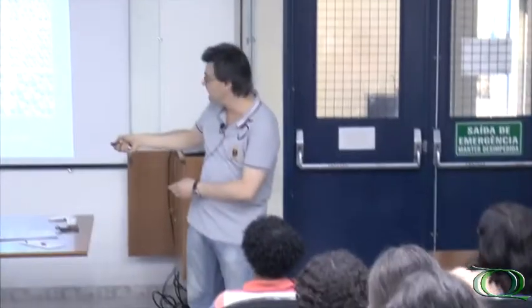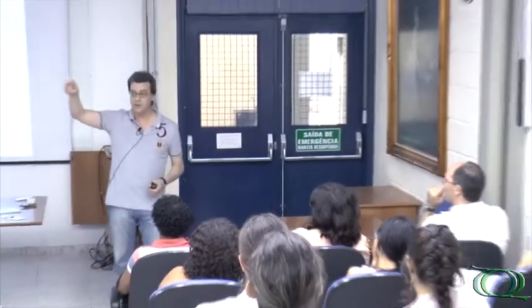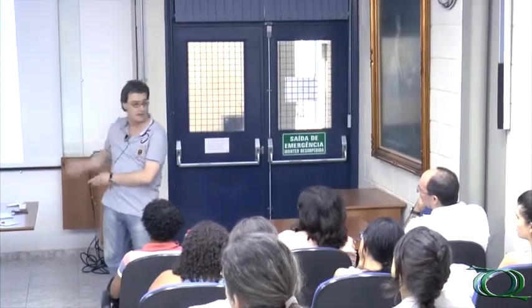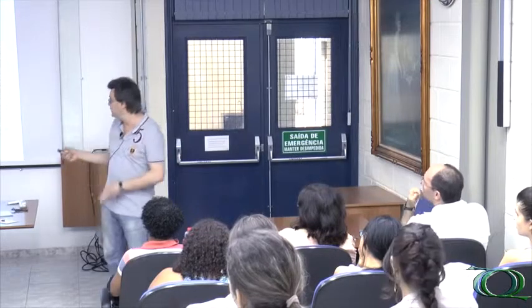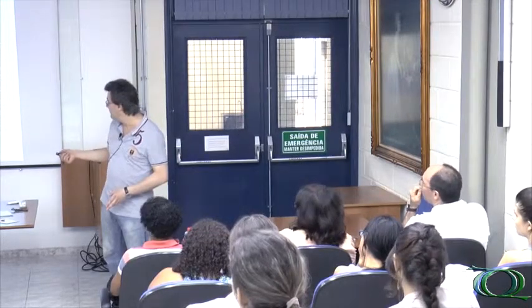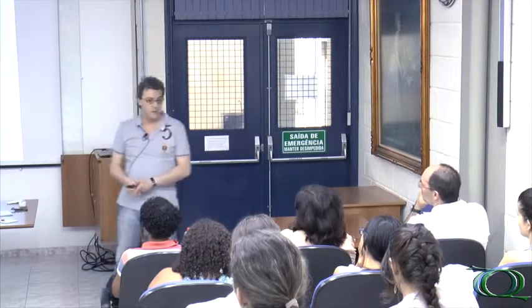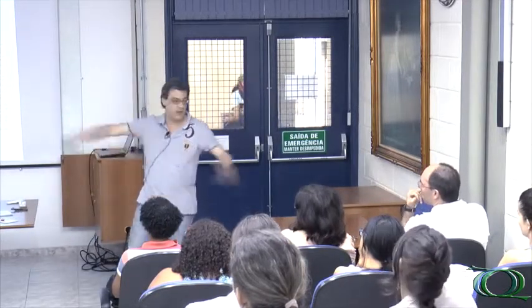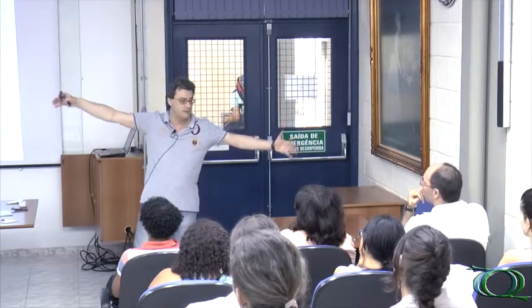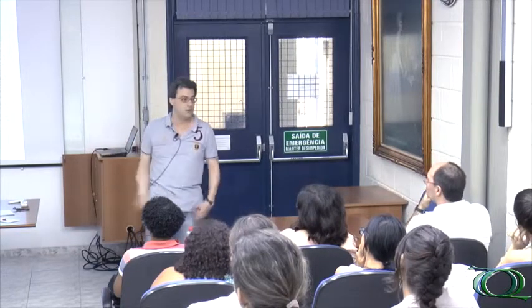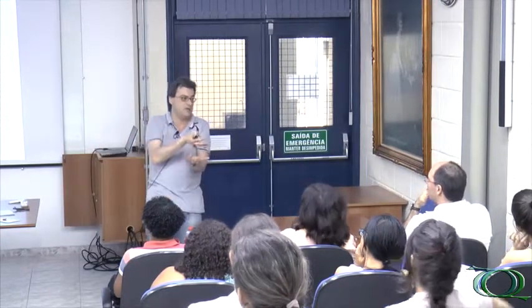And I am pretty sure that if we do that experiment at very small potential intervals, we'd actually see a curve rather than a straight line. So I do think that we have a straight line here where nothing is changing, which is the typical Stark effect. But I am pretty sure that the frequency should change gradually in a curve, and that we are seeing a straight line simply because we are using very, very big potential steps. But we have to repeat this experiment because I am pretty sure that this must be gradual, just as the hydrogen absorption is gradual too.